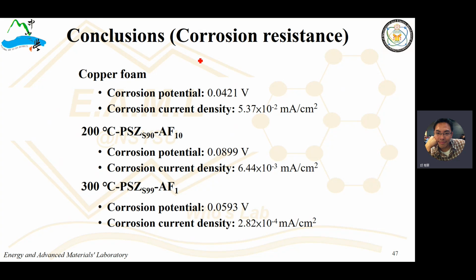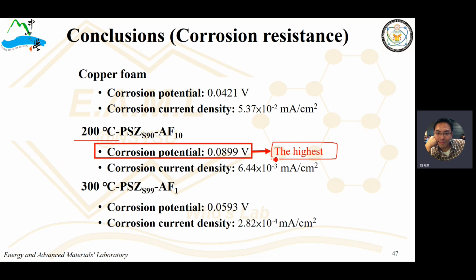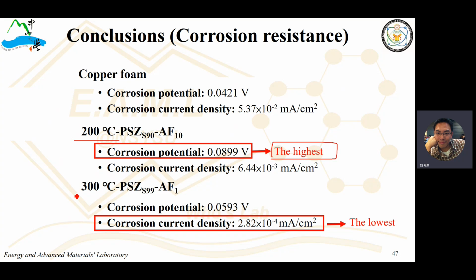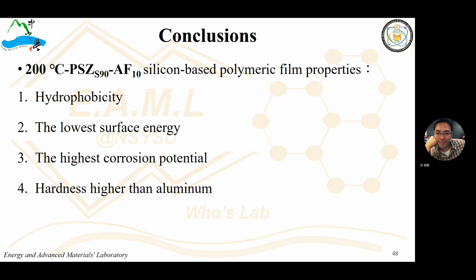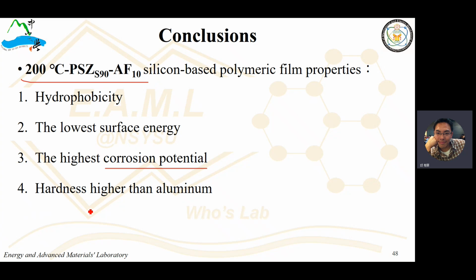For the corrosion resistance test, the coating heated at 200 Celsius has the highest corrosion potential, and the coating heated at 300 Celsius has the lowest corrosion current density. We conclude that when this coating is crosslinked at 200 Celsius, it has increased hydrophobicity, the lowest surface energy and the highest corrosion potential, and its hardness is higher than aluminum.